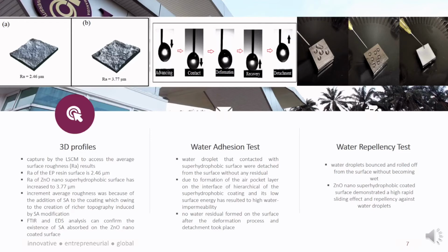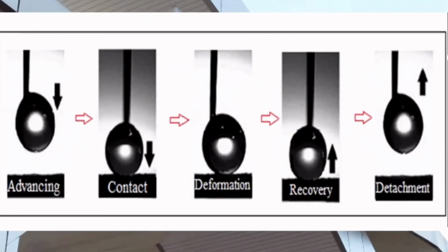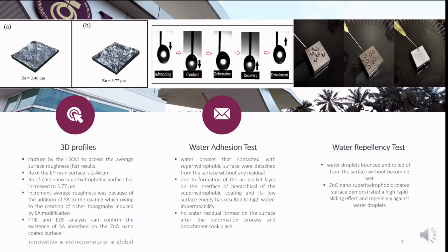EDS and FTIR analysis were used to further the investigation. FTIR and EDS analysis can confirm the existence of stearic acid adsorbed on the zinc oxide nano-coated surface. The result of the water adhesion test shows that the water droplet that contacts the superhydrophobic surface was detached from the surface without any residual. This is due to the formation of an air pocket layer at the interface of this superhydrophobic coating, and its low surface energy has resulted in its water impermeability. No water residual formed on the surface after the deformation process and detachment took place, proof that this zinc oxide nano superhydrophobic film has a low water adhesion.